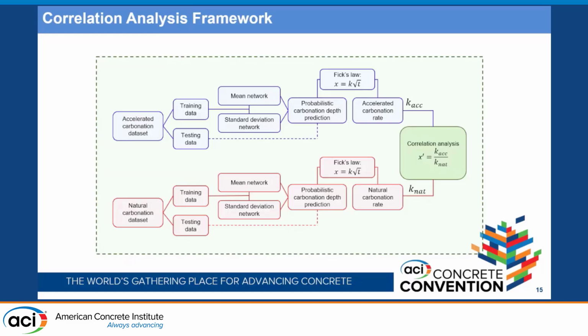And this is the overall framework that we use to find the correlation between the accelerated and natural carbonation. Once we have our model and we can predict the carbonation depths, then we can use Fick's law to find the carbonation rates for both the accelerated and natural carbonation models. And then we can find this correlation index, which is the ratio of accelerated to natural carbonation rates.